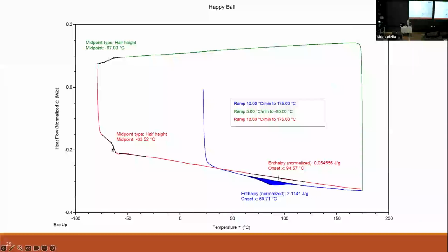So, glass transition in a polymer. A glassy polymer is a polymer that's hard, more or less. We have physical crosslinks that prevent the chains from sliding past each other. So a ping pong ball is a good example of a glassy polymer. It'll spring together and spring back when you bounce it off the ground. A rubbery polymer will also bounce back, as we see. But we have this other rubber that doesn't bounce. So it's neither glassy nor rubbery. That's our first hint. So we see the glass transition is at -60, which means it's rubbery above that temperature. So we see for the rubber ball, it's bouncy, it's rubbery.